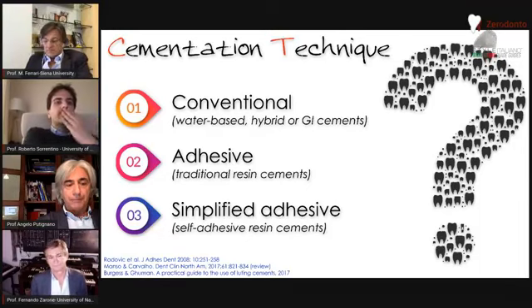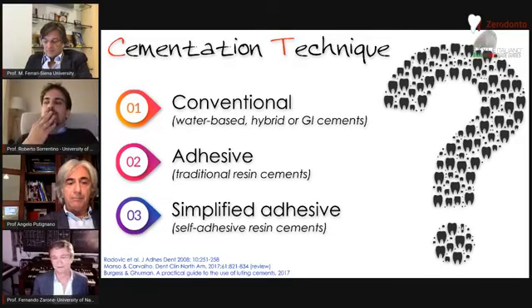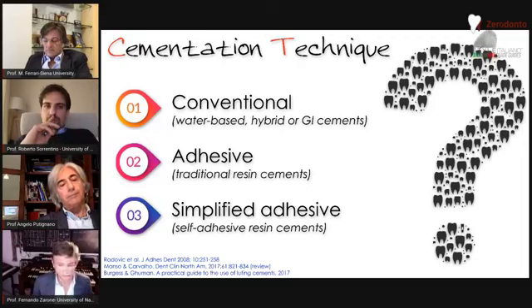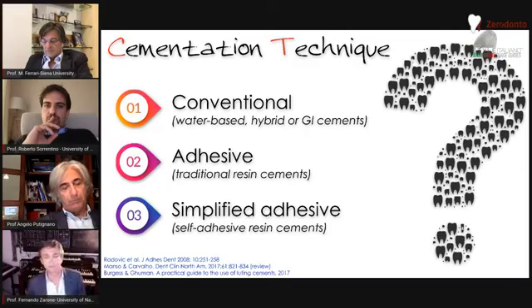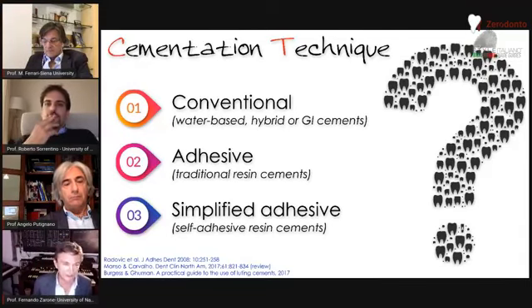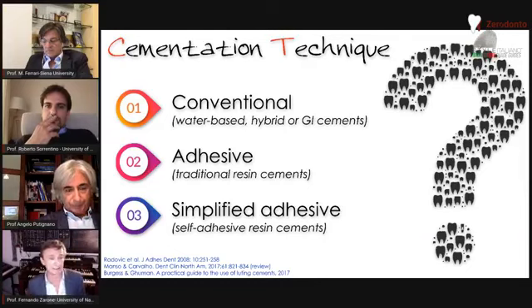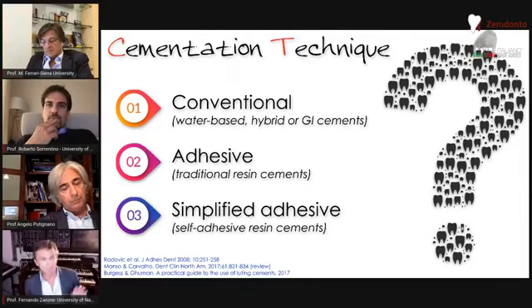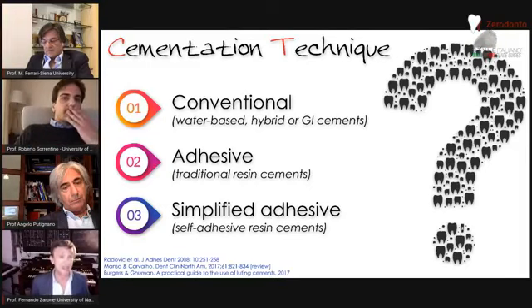Professor Zarone? Naturally, classic adhesive cementation. I would go for dual cure, but it's the same. After using try-in paste with a very approximate trial of shade, just 20 seconds of hydrofluoric acid in the intaglio, then distilled water in an ultrasonic bath, and everything is okay. Avoiding overetching of the intaglio with longer exposure to strong acid, because it can induce damage, so that's a very, very important step, etching the ceramic, but naturally adhesion, naturally with rubber dam.